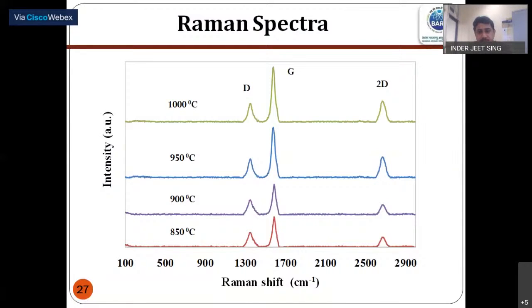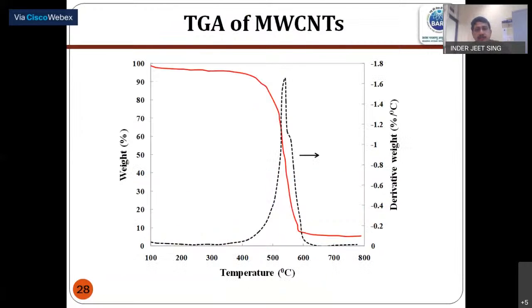So we get a typical Raman spectrum at different temperatures, and we do TG. TG means thermogravimetric. Here we can find how in an oxygen atmosphere there is a weight loss, and if we plot the differential, we get typically 2 peaks. Generally, the end of a carbon nanotube, which is a cap type of thing, and some of the defects which are present, being high energetic areas, start oxidizing first, and the walls of the carbon nanotubes which are well aligned start oxidizing later. So we generally get 1 peak corresponding to the high energy portion oxidation. Second is the relatively stable phase oxidation.